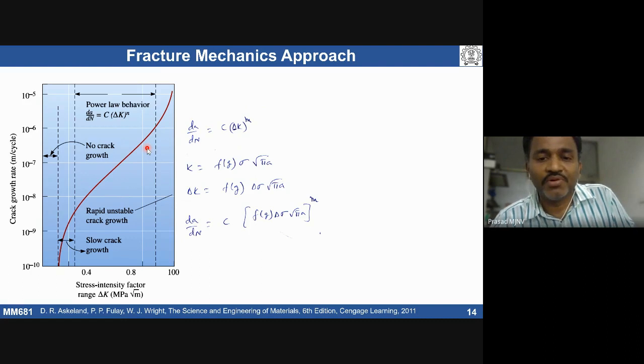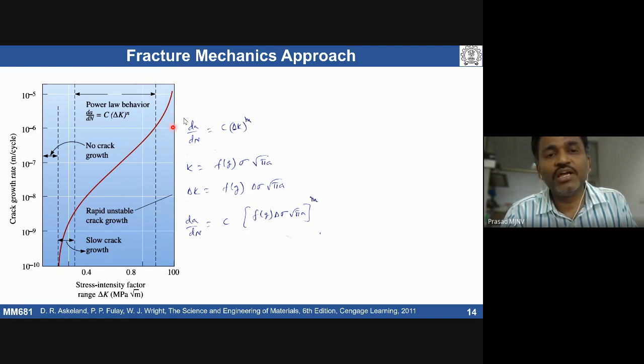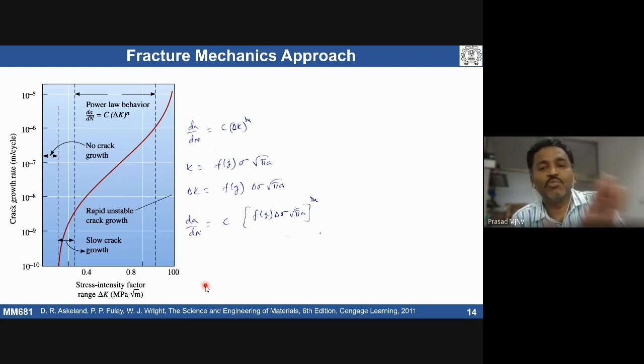After that you have to stop, or replace the component with some other material. So the component should not go to a rapid, unstable crack growth regime. If it is within this regime, then it's fine, the component is safe. That's how people, using this Paris law, can estimate how many number of cycles are required for the allowable crack length.